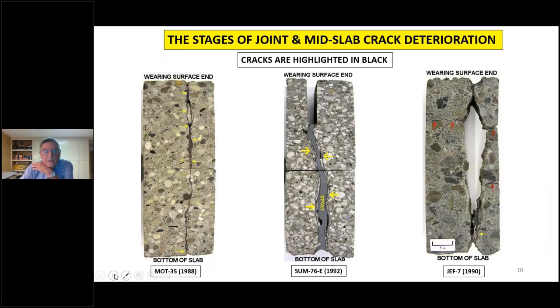So here, these include cores taken through cracks, the one on the right and the left, mid-slab cracks, and then the one in the middle taken from a joint. You can see at the bottom where these came from. In the earliest stage of this, these are lapped surfaces of the cores. This is a 3/8 gravel and 3/8 limestone, and it's a 1-inch slag aggregate on the right.